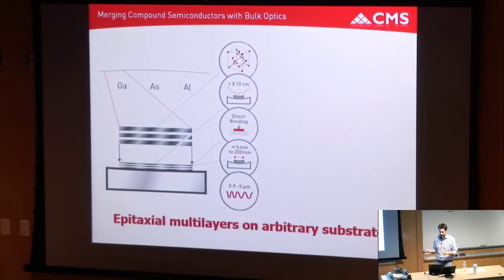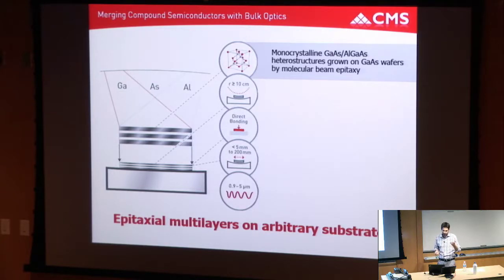so from a big picture point of view, the basic concept is really merging these two sort of disparate fields. There's extremely high quality semiconductor material, semiconductor microfabrication processes, and traditional bulk optics. And there's a lot of overlap between these two areas, but you don't really see this come together in a single device or single focus area. So what we do is we grow, leveraging 40, 50 years of epitaxial growth development, ultra-high purity, single crystal gallium arsenide and aluminum gallium arsenide multilayers, and take these heterostructures grown on a base gallium arsenide seed wafer.